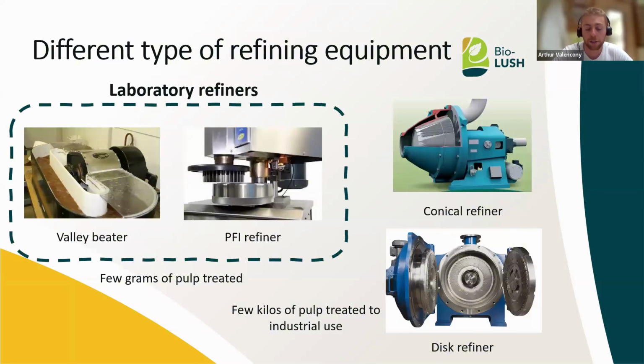Okay, next slide. So, different types of refiners. At laboratory scale, we have the Valley Beater and the PFI refiner, two refiners that are really useful to compare different pulps at a laboratory scale with a few grams of pulp treated, so quite easy to manage. And at industrial or pilot scale, we have the conical refiner or the disc refiner. But I think the most used is the disc refiner with a double disc construction, and it is really efficient, and it really improves the mechanical properties of fibers.